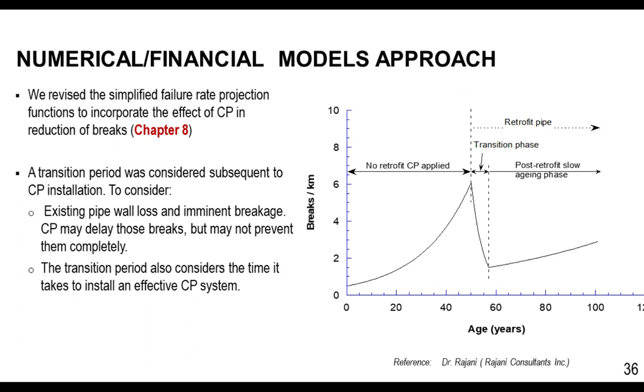We basically took these functions and revised them to incorporate the effect of CP on the reduction of the breaks. We don't have time to get into the detail of the equation and the parameters and assumptions that go into it, but one thing that I just want to mention here is the transition period that was considered subsequent to the CP installation. As you see in this graph on the right, after installation, pipe is going to age, and the number of breaks increases as the pipe ages.